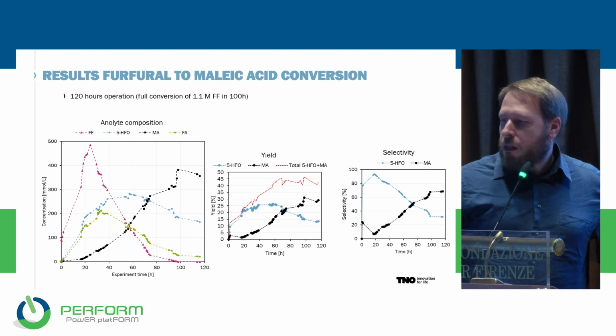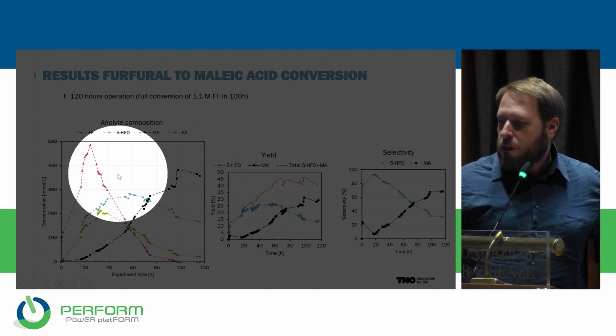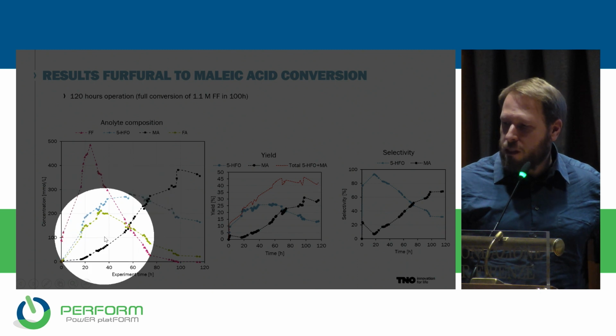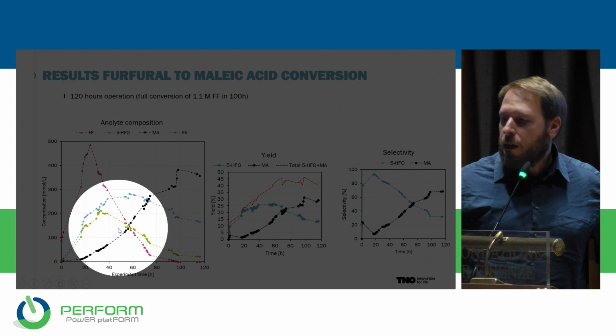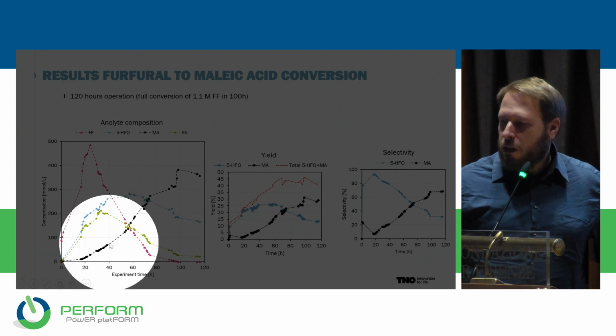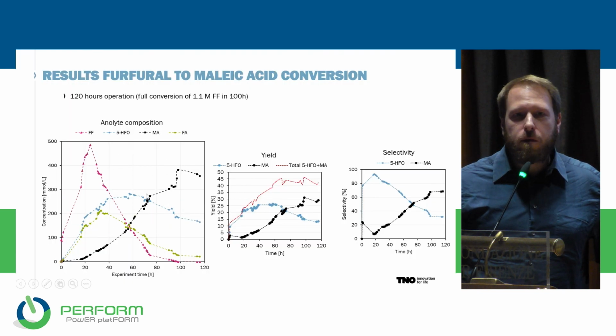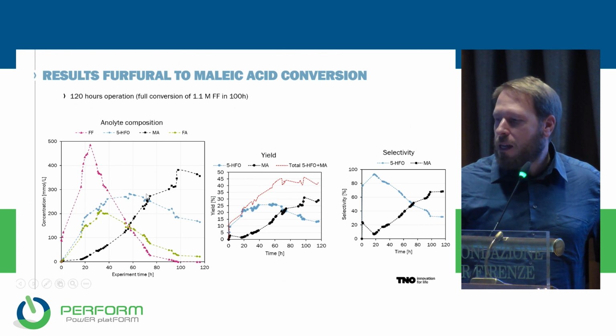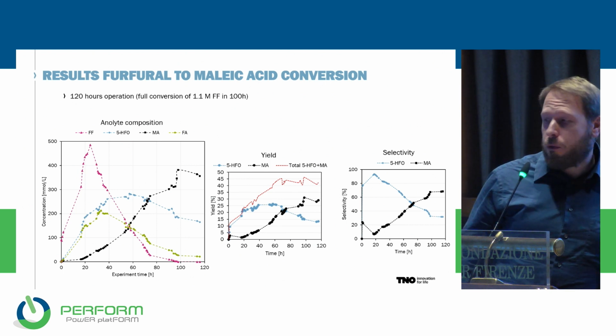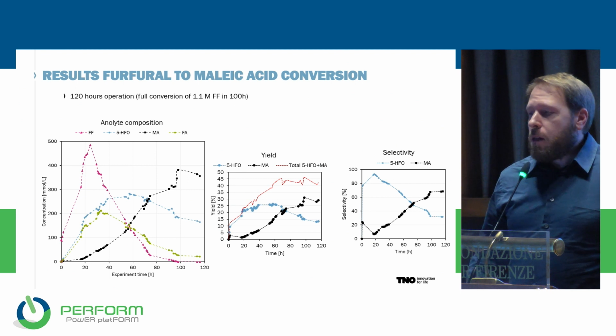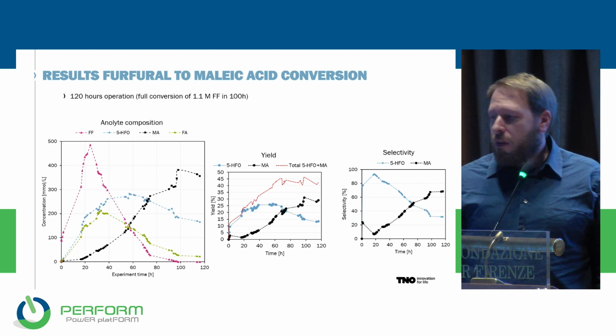But aside from this small issue, after a certain time, when we start to build up a bit of concentration of 5HFO, and we start running lower in concentration of furfural, then at this point is where we actually start making maleic acid directly from the conversion of 5HFO. Yeah, so this all looks very nice and very promising.